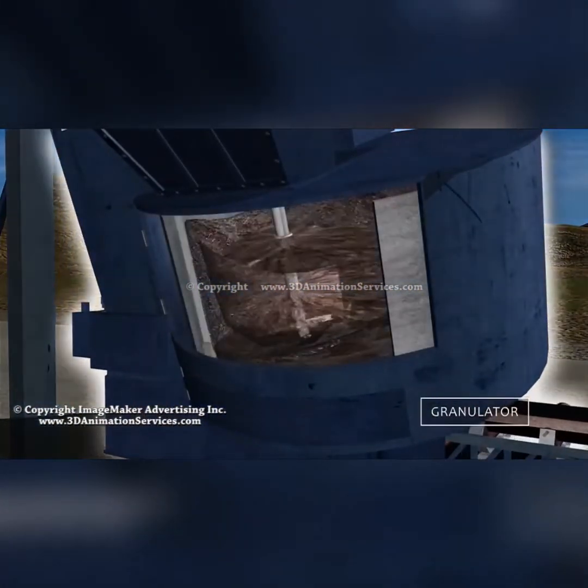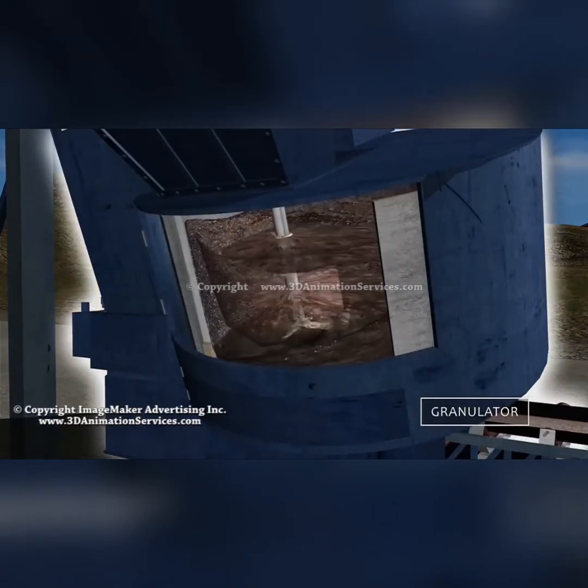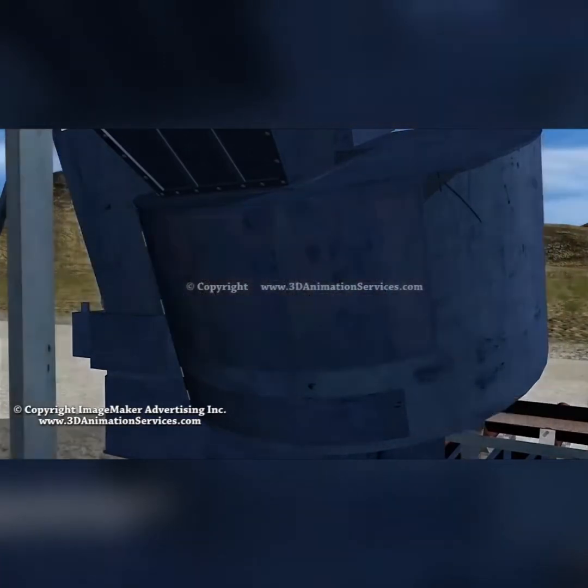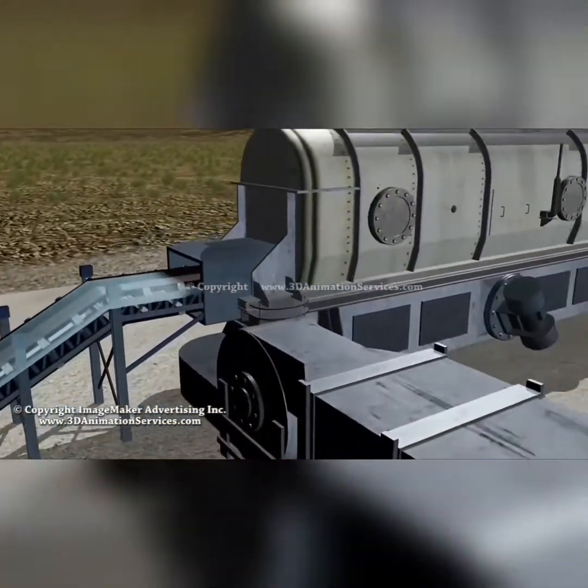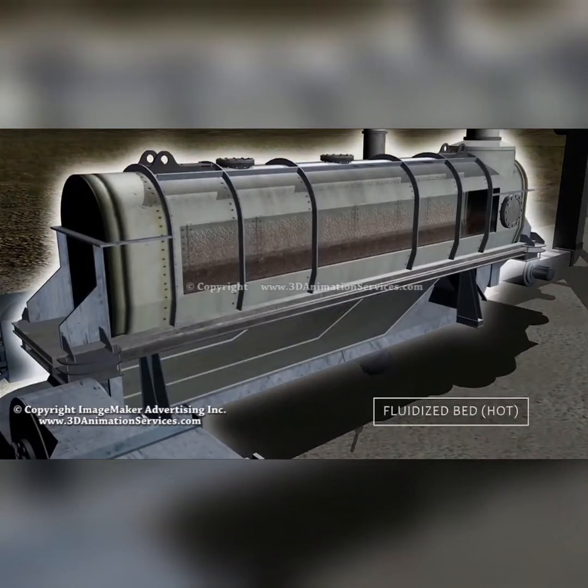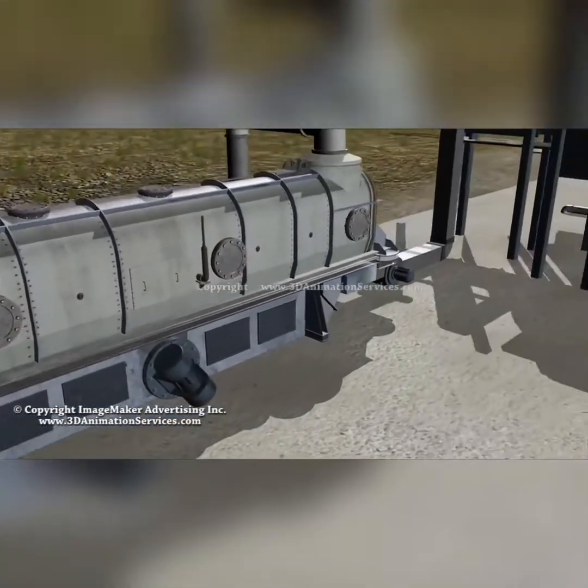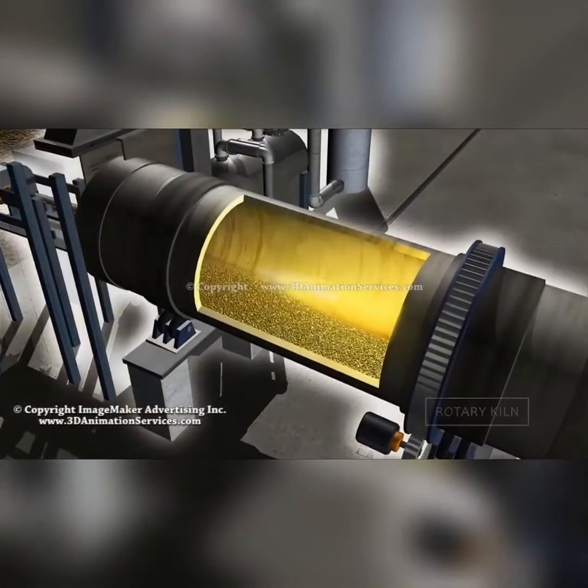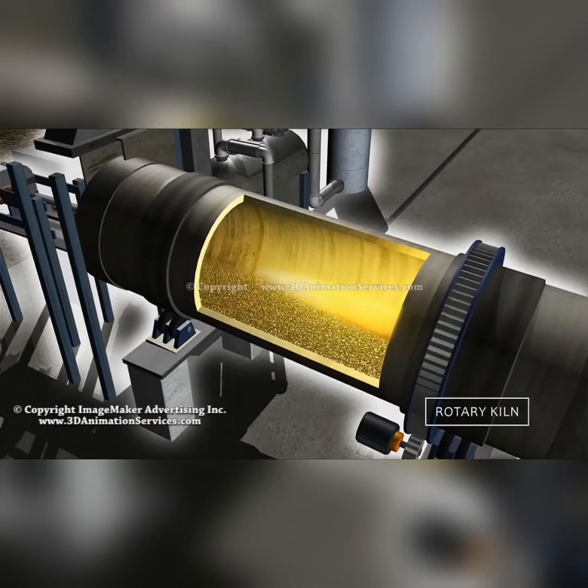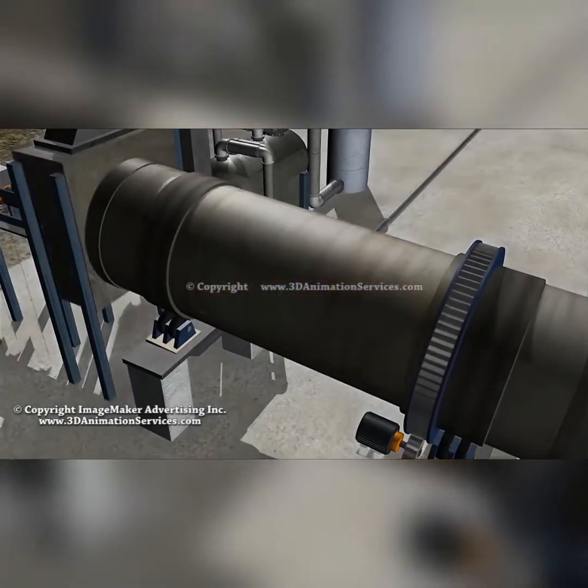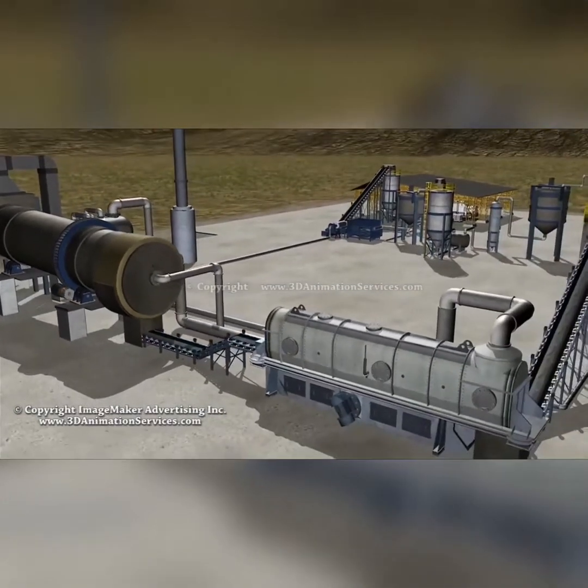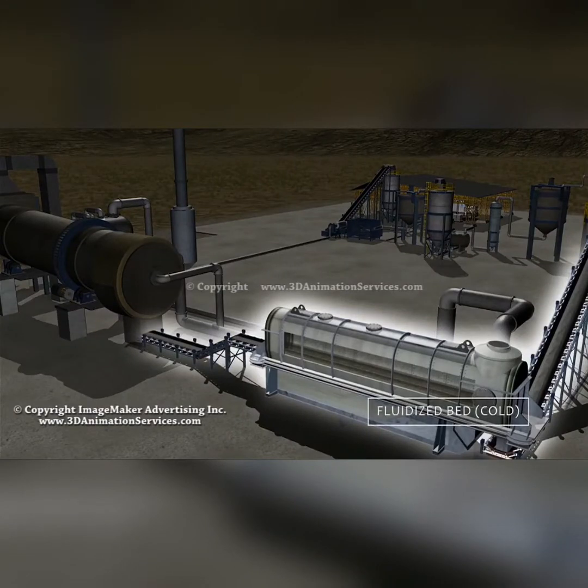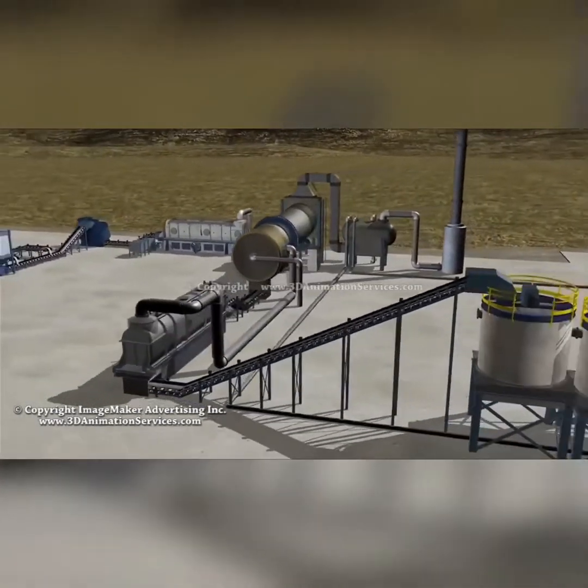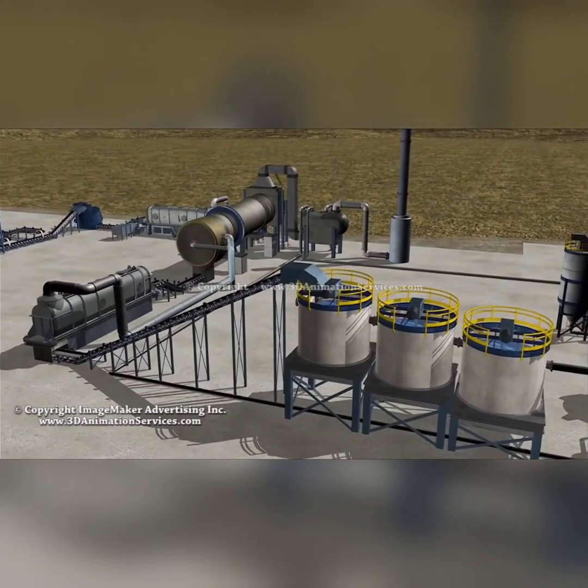They are then mixed with the ore in a specialty granulator to form granules. The granules are dried with hot gases on their way to the calciner. At around 1000 degrees centigrade, lithium, sodium, and potassium, the alkali metals in the ore, are converted to water-soluble sulfates. The resulting calcine is then air-cooled in a fluidized bed cooler. Preheated air from the cooler is added to the calciner, while the calciner off gas is used to produce steam for the downstream evaporation and drying units.